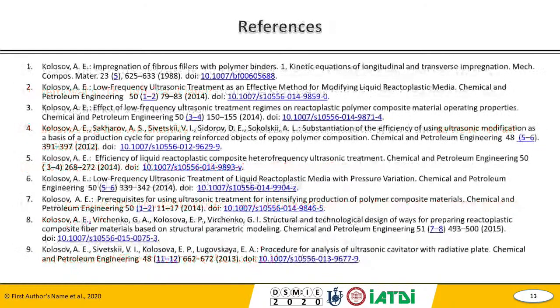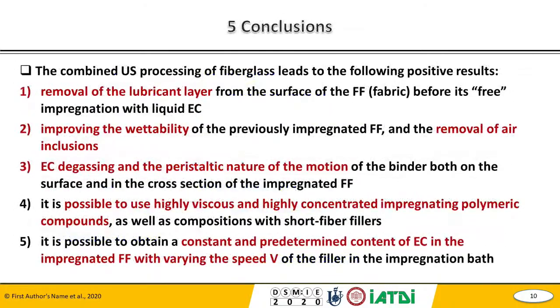The next result is epoxy composition degassing and the peristaltic nature of the motion of the binder, both of the surface and the cross-section of the impregnated filaments. Next, it is possible to use highly viscous and highly concentrated impregnating polymer compounds, as well as compositions with short fiber fillers. And the last one is that it is possible to obtain a constant and, most importantly, predetermined content of epoxy composition in the impregnated fiber filaments with varying pulling speed of the filler in the impregnation bath.